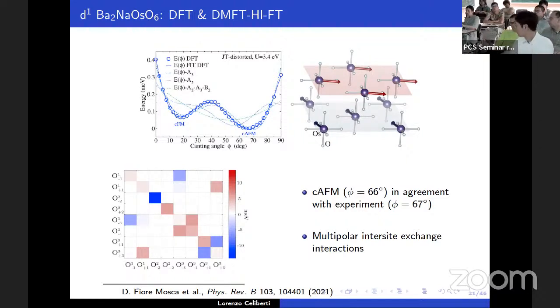We well understand how the system would react if we apply external magnetic fields when we have only conventional magnetic order, this antiferromagnet. Can I find some traces of this hidden order when I apply my field, for example in some phase transition fields? If I try, for example, to polarize my magnetic moments with external fields, we can calculate, without these hidden orders, a critical field which corresponds to this phase transition. Can I observe some traces of the hidden order in such quantities?